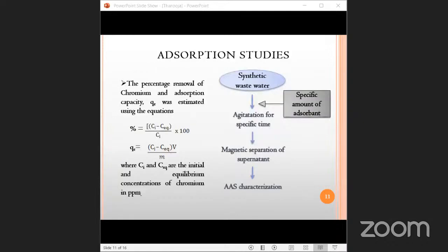Now, the adsorption studies. The effect of the adsorption parameters like adsorbent dose, contact time, and initial ion concentration on the removal of chromium-6 ions was studied by batch adsorption studies. Synthetic wastewater containing chromium-6 ions was prepared by dissolving potassium dichromate in distilled water. To 20 ml of wastewater, the desired amount of adsorbent was added and agitated for a specific time. After magnetic separation, the concentration of the metal ions in the supernatant was determined using an atomic absorption spectrophotometer. The percentage removal of chromium and adsorption capacity was estimated using the equations given.